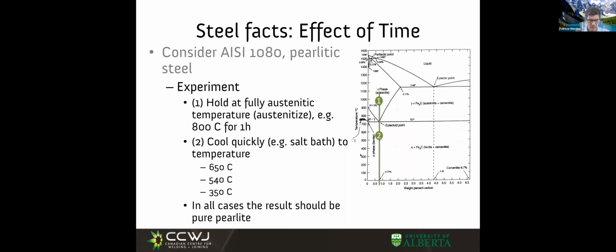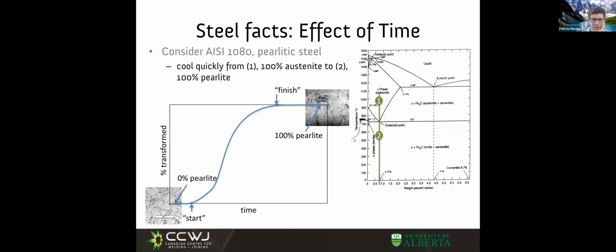Let's see what happens if I cool down and hold at that temperature. Cool quickly - I know that in the end the result should be pearlite. In this graph, to represent the effect of time, the horizontal axis is time and the vertical axis is percent transformed. At time 0, the exact moment I put it in my quench, since atoms take some time to transform, I have 0% transformed.